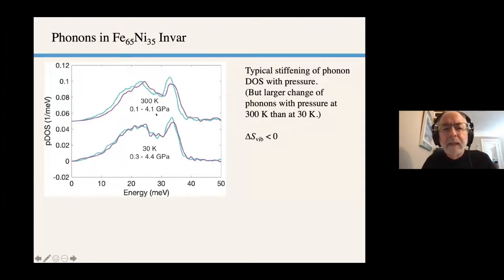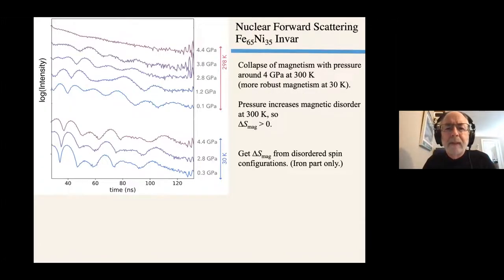This is over the interesting range of about 0 to 4 GPa. And you can see what happens. The phonons get stiffer as we apply pressure. So the frequencies go up, the atoms don't move as much, and the entropy goes down. So as we apply pressure, the vibrational entropy is less at higher pressures than at low pressure. At 30 Kelvin, things didn't change so much. It's interesting, but we haven't analyzed the 30 Kelvin data yet. I'll just show you the room temperature results.